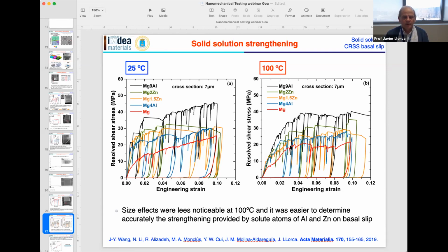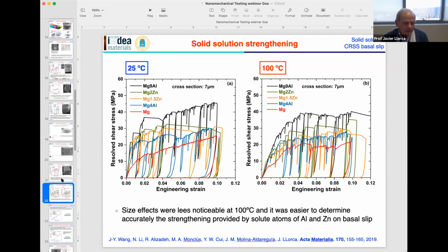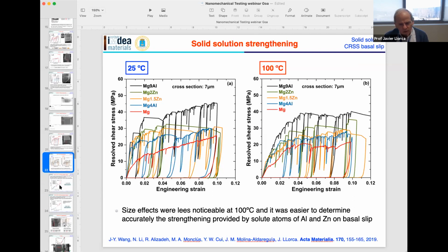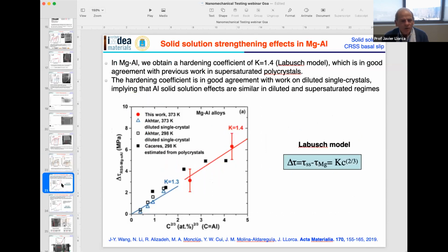So this is really a high throughput methodology, because if you want to obtain the critical resolved shear stress for basal slip in these four different magnesium aluminum and magnesium zinc alloys using standard techniques, you would have to cast a single crystal, carry out the mechanical test, and it would be very, very time consuming and very expensive. So let's see how it looks.